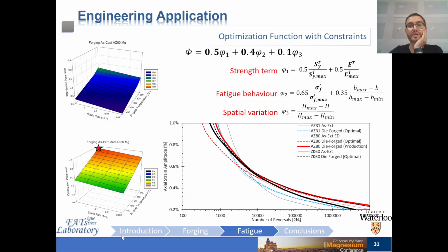Finally, if we impose some constraints upon this optimization surface that you see here, such as the extremities of very low temperatures and very high strain rates, we observe cracking within the material. So that's one constraint that we can impose here by this gray area. Secondly, at temperatures that exceed 426 degrees Celsius, including the heat of deformation, incipient melting may occur in AZ80. So we know that results in inferior material properties, as you might have some microscopic defects within the forged component. So we've excluded this area here.